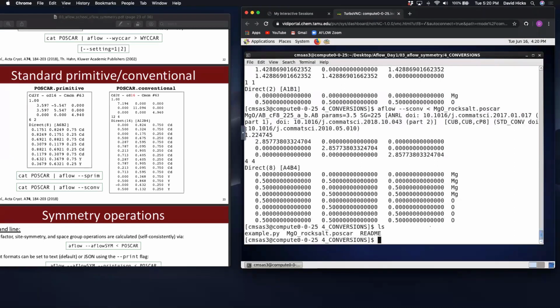I can add to the phonon calculation point. When you have a very elongated primitive cell and you create a supercell that you need for phonons, VASP might not be able to convert your structure because the structure is so weird and elongated that VASP has trouble figuring out what's going on and getting the structure to converge. So a conventional cell actually helps when it's more orthogonal for VASP.